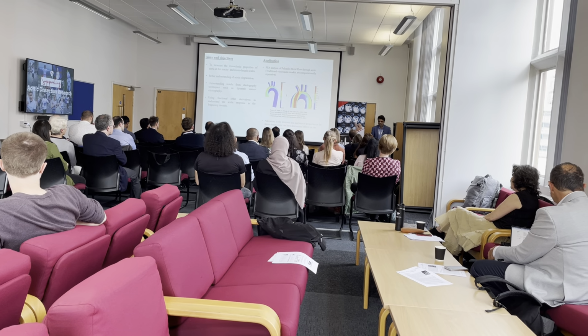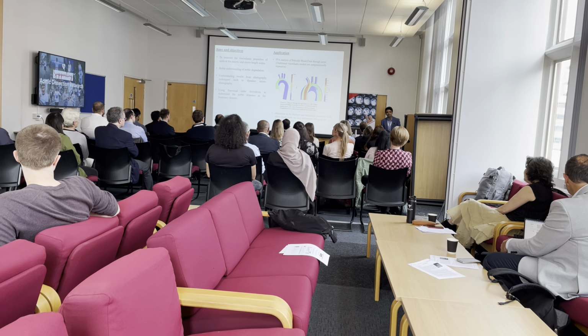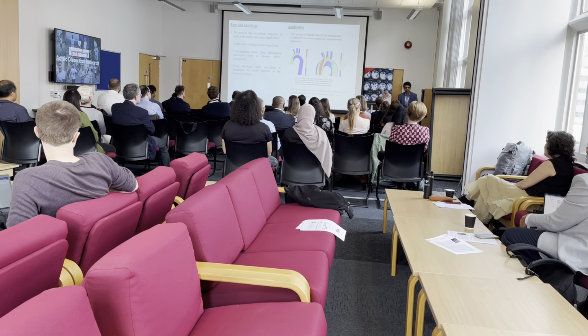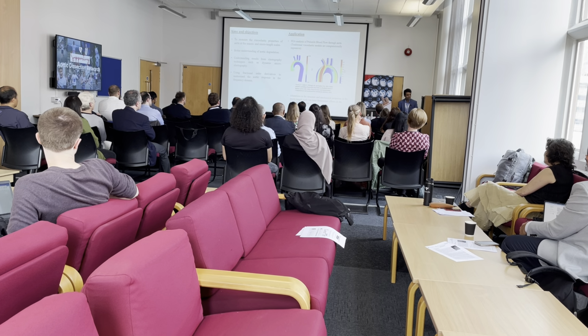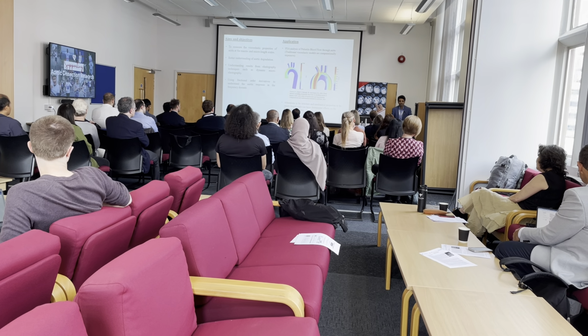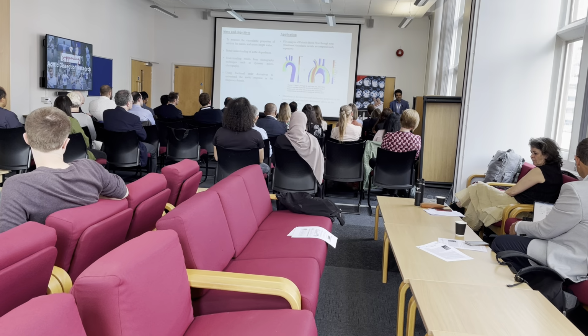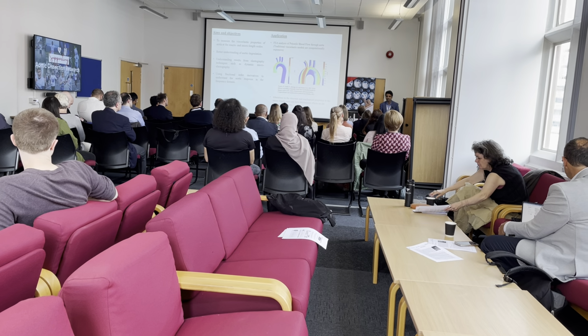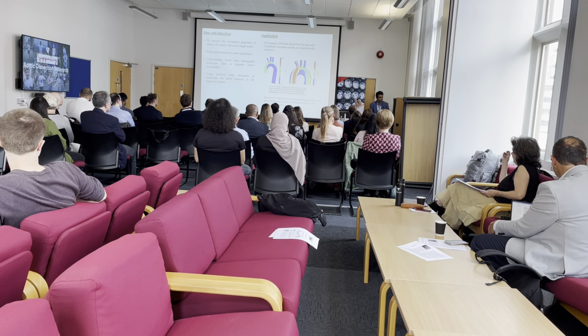Then we were using these fractional order derivative models, because compared to traditional viscoelastic models where we need a large number of parameters, we can actually use springpots, which are like fractional order elements, where we can characterize the properties of aorta in the frequency and time domain by using fewer parameters.